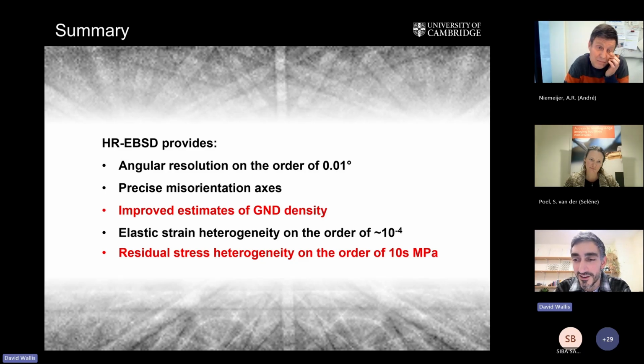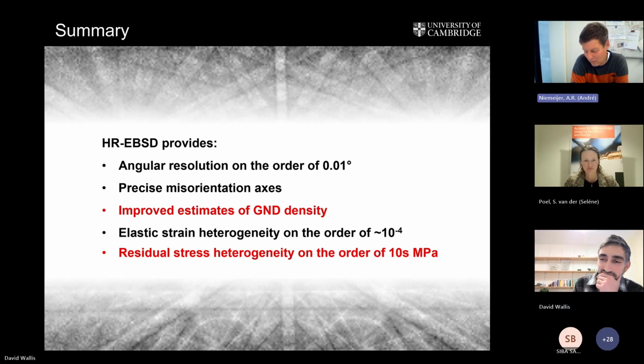So I guess you're thinking more nanoscale. Perhaps, yeah. What's the lowest grain size you've tried successfully? We've mapped things that are like 1 micron, but that would be like forsterite or something, which doesn't damage as much. On metals, people have definitely done a few hundred nanometers, because you can go down to a step size of like 50 nanometers or something. It depends a lot on the material. Yeah, all right, thanks.